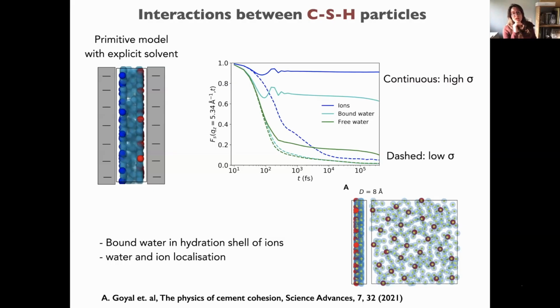So in the case of high surface charge, which is the case of CSH, both the ions and the bound water, which is the hydration shell, reach a plateau. So they stay correlated for a very long time.